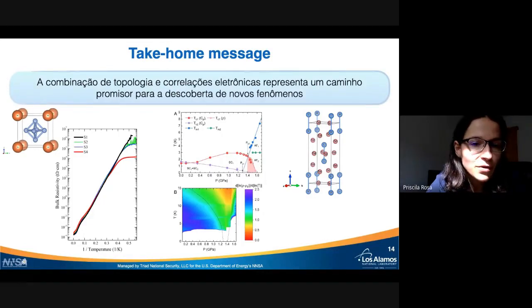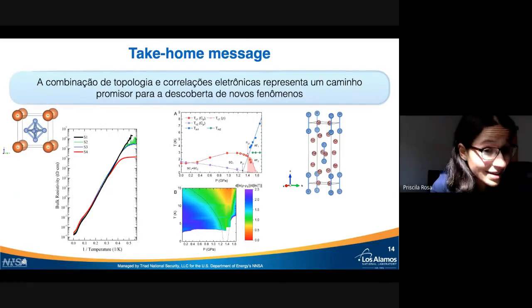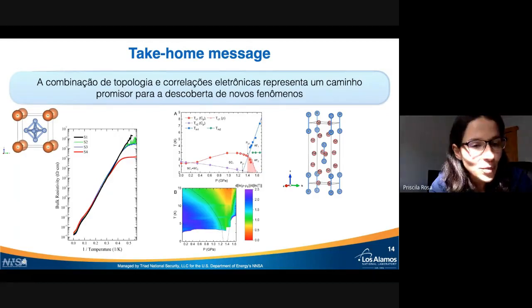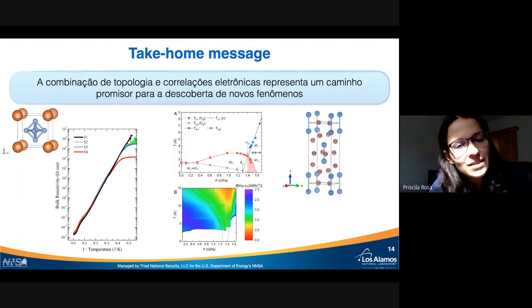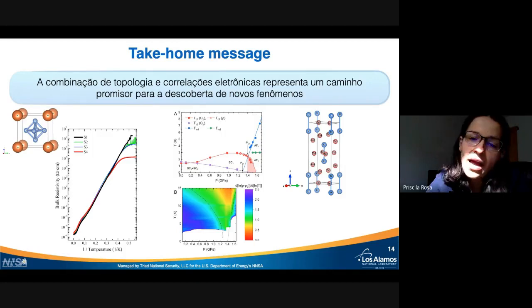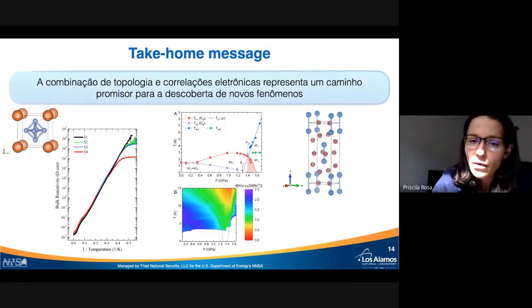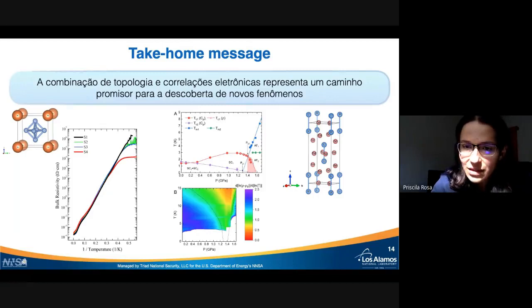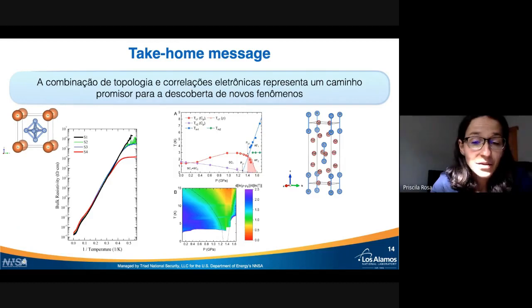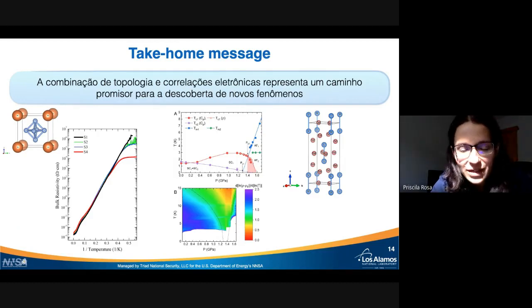So I showed you the example of samarium B6, which was the first actually topological Kondo insulator candidate. And it's a simple cubic material that shows a very nice insulating DC bulk. I also showed you the example of uranium tellurium 2, which is a more complicated orthorhombic material. Very interesting. There are two superconducting transitions that cross each other, meaning that they're competing. There's a quantum critical point above which magnetism shows up. And there's still many open questions in the field.